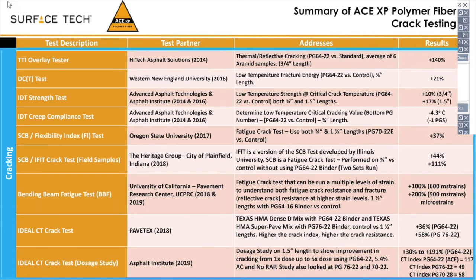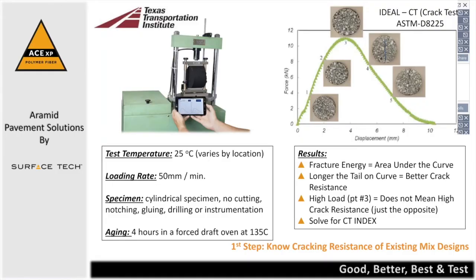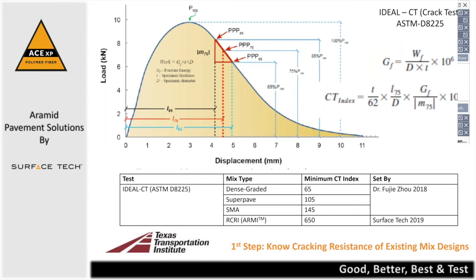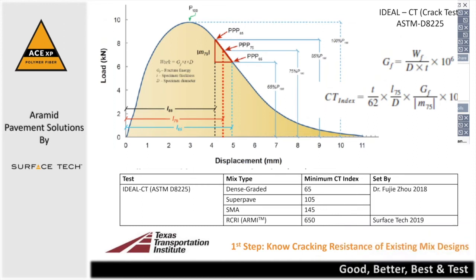So when we say 30 to 50% improvement in crack performance, it's because every one of those tests has come back and shown that. So we feel comfortable moving away from some of the more complicated tests that only certain people can run and that are very expensive, to landing on ideal CT. Just as a reminder, here's the test, here's how we're going to run it. The first thing is to know how your existing mix performs in this test. Some of the values that Dr. Fujizawa set are here in the table early on, and these will move around a little bit depending on where you are in the country. And Bill, you were working with Fuji on that. How's that coming? The regional look at the CT index around the country?